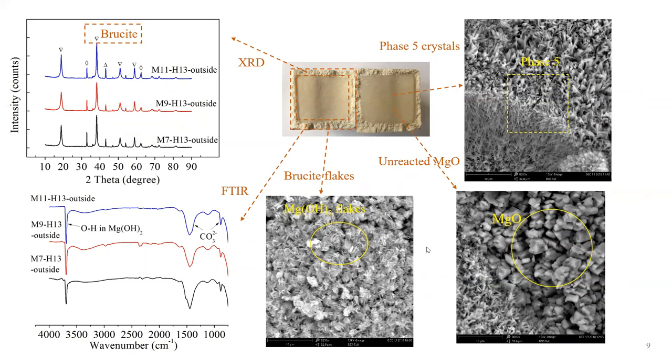And in this figure, we do more analysis, including this XRD and then this SEM analysis. This is the cross-section of the MOC after immersing in water for 28 days. You can see this is the core part. The core part shows the phase 5 crystal, which are needle-like phases. This is the phase 5, which is the desired phase, which keeps the material stable.